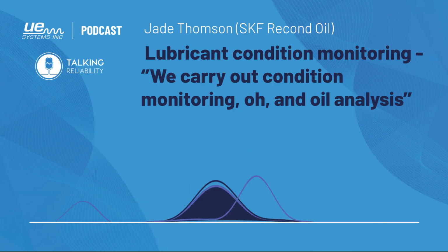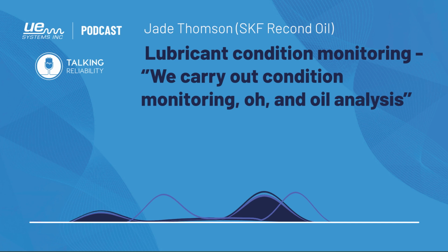And then oil changes, when they are carried out. If we skip back to this slide, on the right, I know there's only been oil top-ups there. If there's been an oil change or a seal change, it massively changes the trends, and it ends up looking like a completely different lubricant and a completely different set of results. So it's really important to feed back to the lab when any maintenance activities have been carried out. And also history: if you forget to let the lab know exactly when something happens or when something changes, and also what's planned in the future.